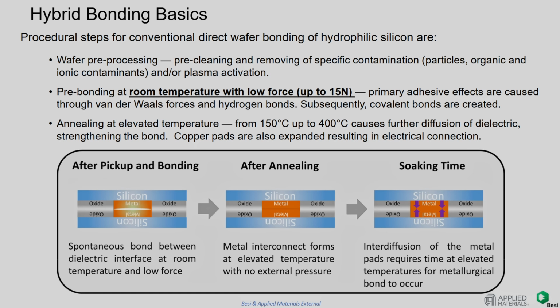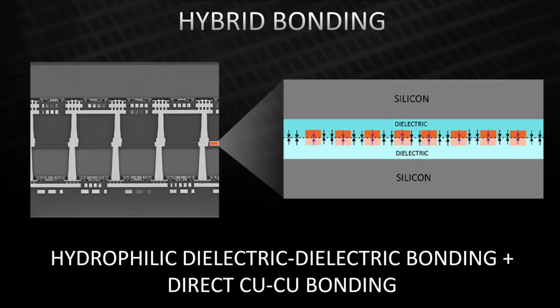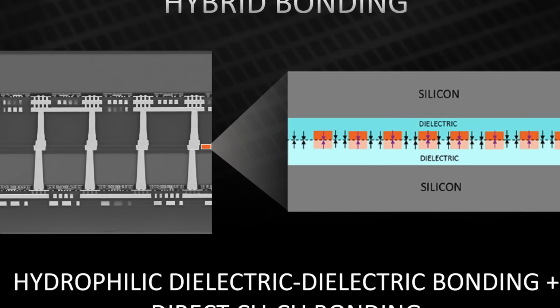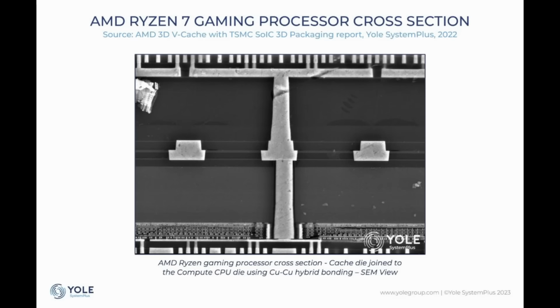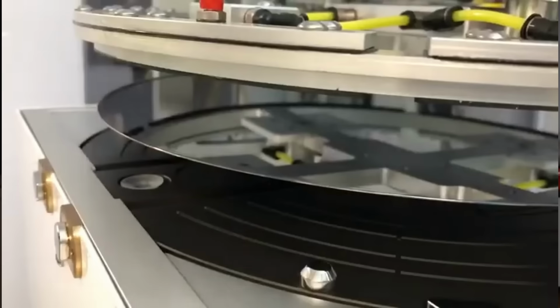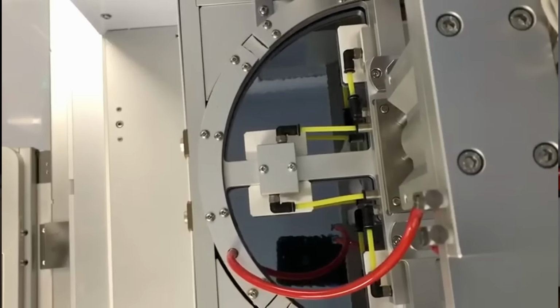The result is that the copper pads on both chips are now fused with each other, forming a single electrical interconnect. And they are isolated from each other by the surrounding dielectric material. This bond itself is strong enough to keep both chips bonded to each other without any additional support. This process flow is why hybrid bonding is so special. It connects two chips in the most straightforward way by directly forming copper-to-copper bonds without the use of solder. You are basically fusing parts of the metal layers of both chips.